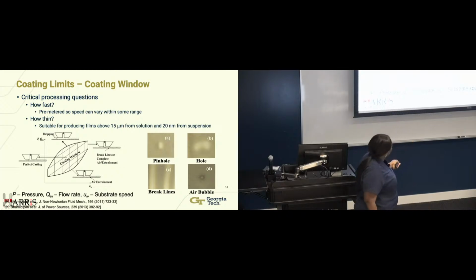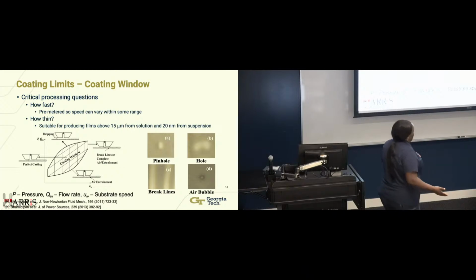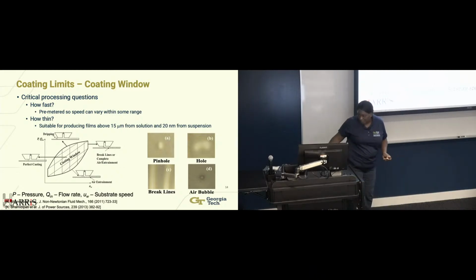Then, if your speed is too high, then you're dragging the fluid too fast relative to the pump, and your dynamic contact line shifts. And that shift is what's creating the onset of defects. For example, the air getting dragged in and the pinholes that are subsequently formed, or holes. And if you go super fast, then you'll get break lines, which look like streaks down the center of your material that's coated. And then the air bubbles.